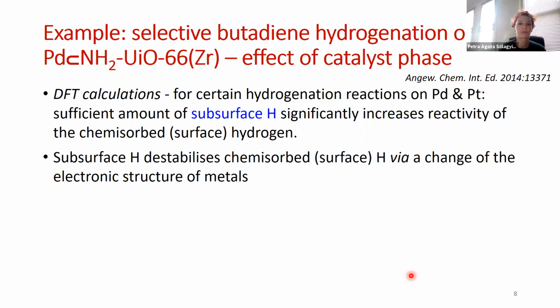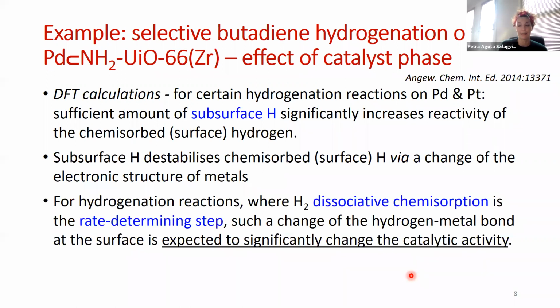And that is going through a kind of destabilization of the surface hydrogen atoms through the subsurface hydrogens, because they change the electronic structure of the metal. And in the case of palladium, it is very straightforward because under hydrogen, interstitial hydride may form. And this is something I will discuss in a little more detail.